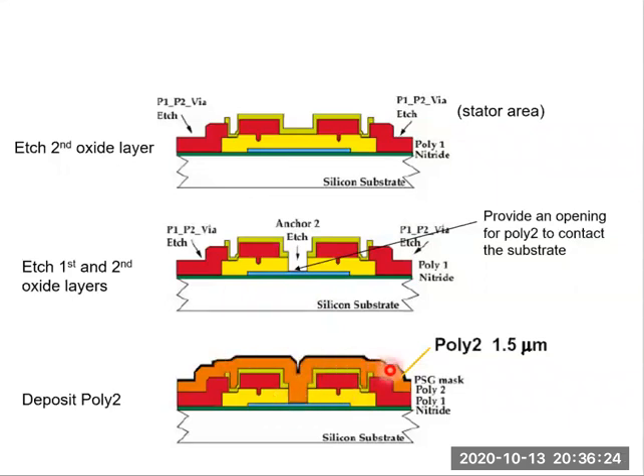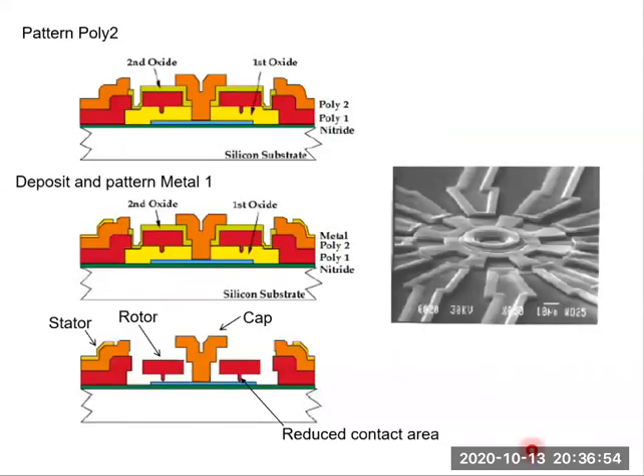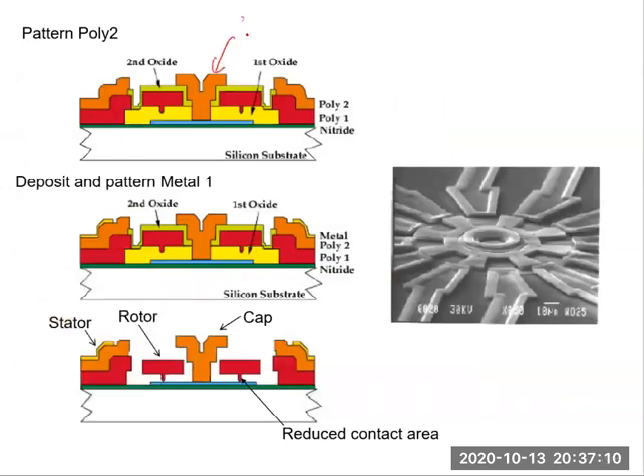Note that above poly 2, a PSG layer is coated. Okay, we call that PSG layer. And high temperature annealing is carried out to reduce stress and to dope poly 2. So poly 2 is also doped by phosphorus. Then pattern the poly 2 layer. So this layer is patterned, is etched. And the central cap is formed here. Right, this is the central cap.